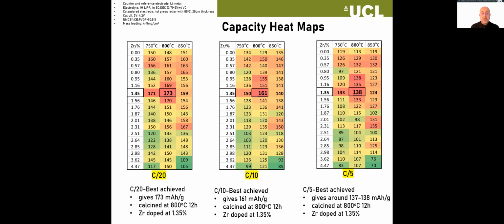The way that I find much easier to look at large amounts of data is to use these heat maps, where red means it's hot, and obviously this suggests there's a high capacity. If you're familiar with battery terminology, this C rate tells you how fast the battery was charged or discharged. So a 1C is a 1 hour charge or discharge. Anything less than 1C, so these three values, would be fractions, so multiple hours. For example, C over 10 would be 10 hours, and C over 20 would be 20 hours.